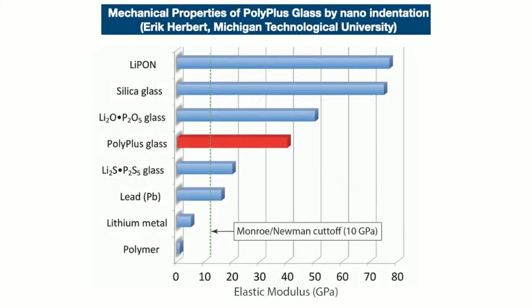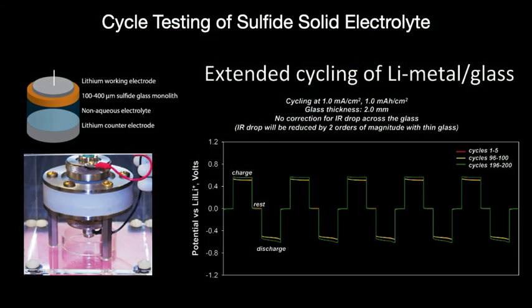We've also looked at the mechanical properties of these glasses. The glass that we're working with is close to the mechanical strength of oxide glasses and much higher than most of these kinds of solid electrolytes. So it's more than tough enough to block lithium dendrites. And in fact, when we test it in these small working cells, you can see that the charge-discharge cycles lay right on top of one another. We don't see any kind of degradation over time.